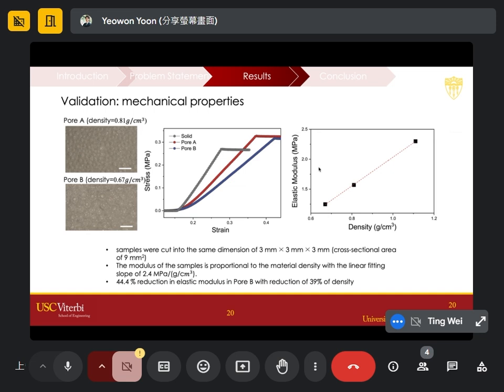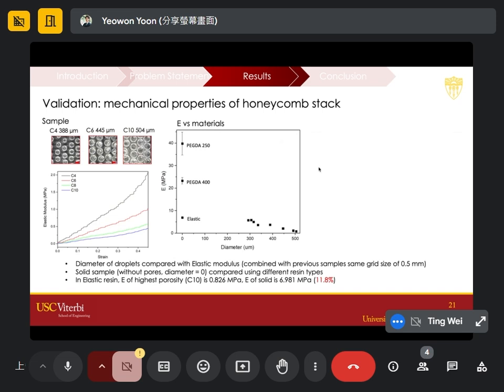So we wanted to push this further to see how much of a change we can achieve using a single material. Here you see examples of printed samples using all different sizes. C4 means 4 droplets into one, having about 400 micron, to C10, about 500 micron. We are doing all the compression tests on different samples, and then here,